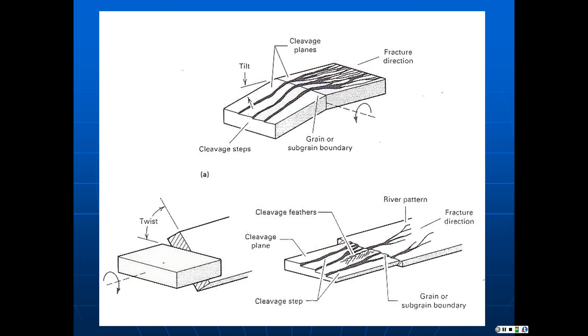How do you know you're looking at cleavage? Classically, cleavage shows river patterns. There are also hackle patterns and cleavage feathers you may see. The river pattern is one of the most conclusive pieces of evidence that you're looking at a cleavage fracture. As cleavage cracks cross grain boundaries, they change direction and there will be some change in their aspect ratio. You'll see facets and also branching of the cracks, usually when they strike an inclusion or defect. What's happening is the crack is propagating on parallel planes — usually close-packed planes — offset by just a few atomic layers. The rivers you see are the steps between those two parallel planes.